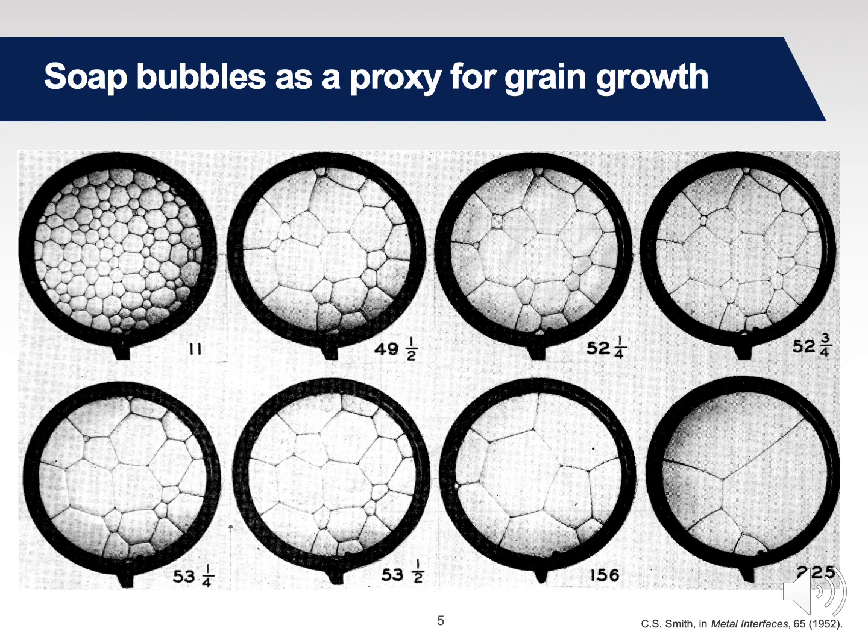This 2D soap froth is representative of a system that is controlled by surface energy or surface tension. And in this case, the law of motion of these boundaries in this soap froth, you can see that the density of boundaries decays over time. All these numbers indicate time steps. This is by Cyril Smith in 1952. And he deduced that the law of motion depends on the energy of these boundaries, of these interfaces, and the curvature. In other words, a capillary force.